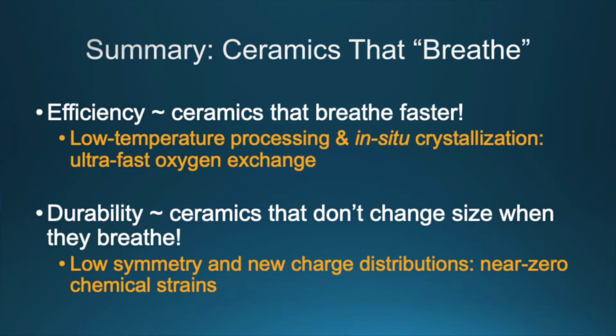So, to summarize, with the efficiency side, this low temperature processing and the in situ crystallization gives really ultra fast oxygen exchange. And I think it's really promising for making these devices much more efficient, especially in the low temperature range. And then for durability, we're figuring out how to make ceramics that don't expand or contract a lot when they breathe. We can do that with low symmetry structures, and we can do that by changing how charge is distributed in the materials.